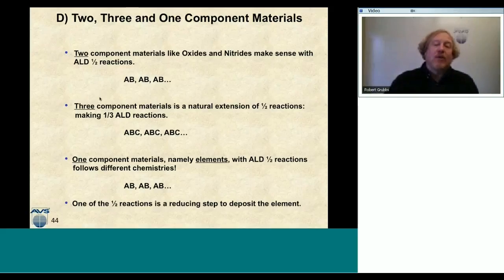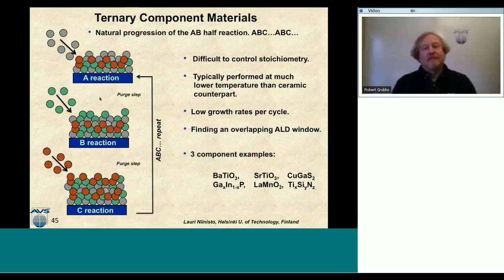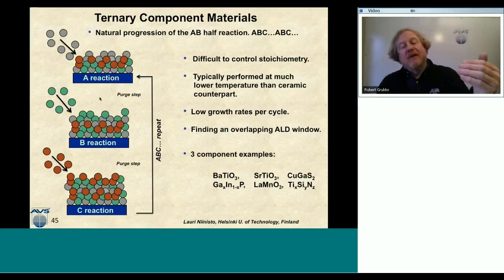So let's take a quick look at three component materials. This is a quick cartoon of ternary materials. As I mentioned, we have an A reaction, a purge step, a B reaction, a purge step, and a C reaction, and a purge step. And then we can repeat this process. But we're really at the mercy of the surface chemistry in terms of controlling the stoichiometry. I would love to be able to control three component stoichiometry, but I'm at the mercy of the surface chemistry to determine how many of these sites I'm filling with the B reaction and how many with the C reaction. So these are somewhat limited.